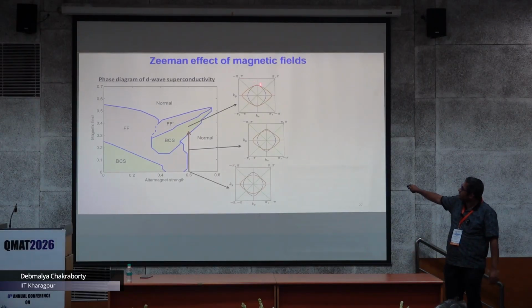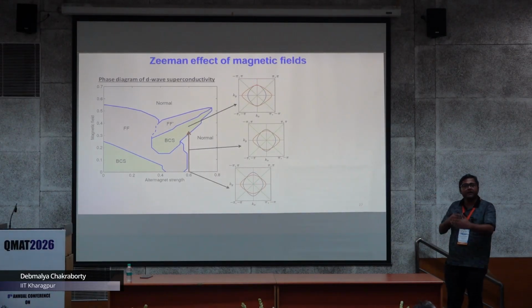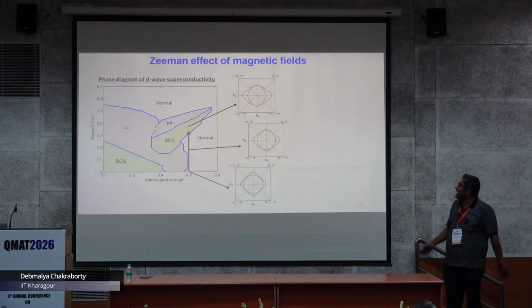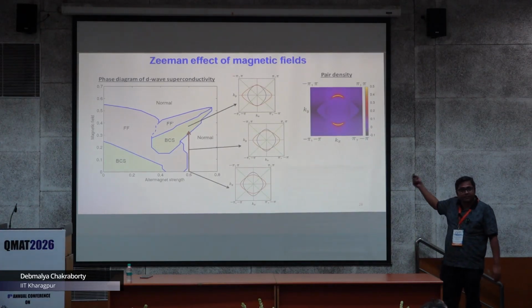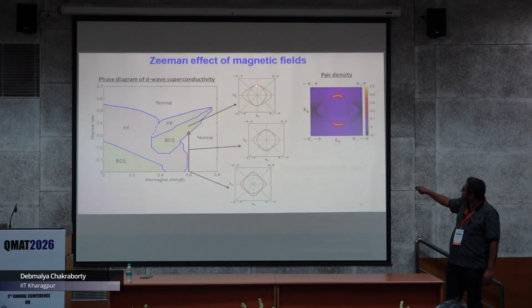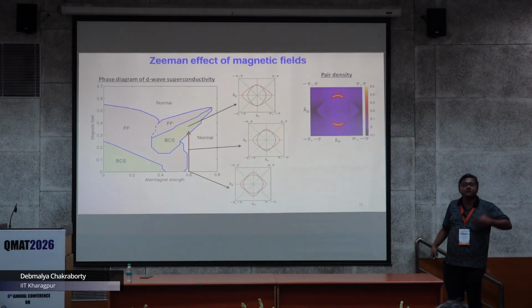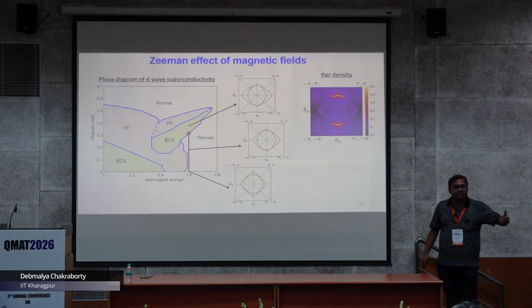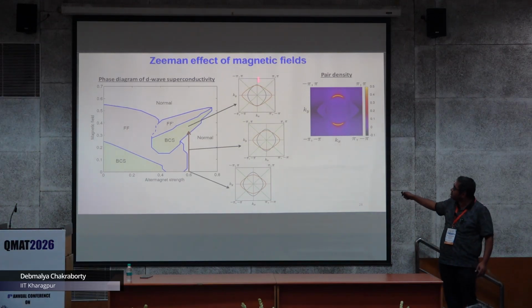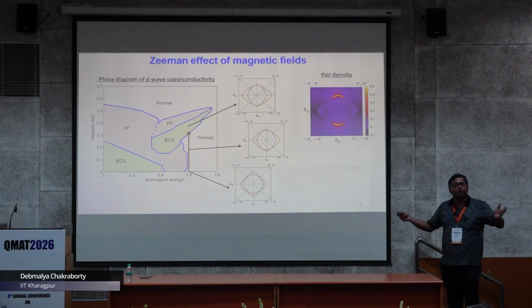So a D wave superconductor has maximum pairing here, and that is the region where it has a degeneracy. And as a result, if you look at again the pair density, you see that at this region you gain superconducting condensation energy, and as a result you start forming superconductivity, and then eventually you will gap that, there will be no nodes.